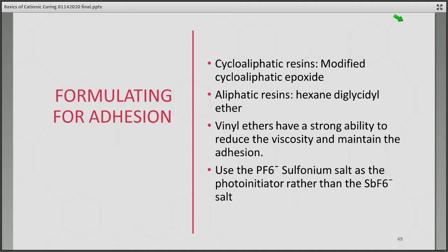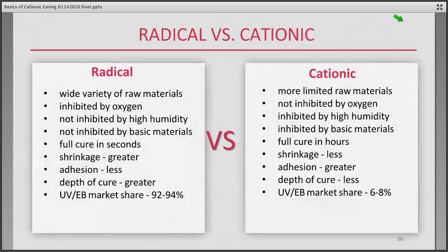Another very simple way is just changing your photoinitiator. It's something that when you formulate we may not think of at first, but perhaps by using the hexafluorophosphate sulfonium salt as photoinitiator instead of the antimonate salt, you usually get a bump in adhesion, primarily through the presence of the phosphorus in your formulation. So that's a real simple way of improving your adhesion, should you need to improve it.